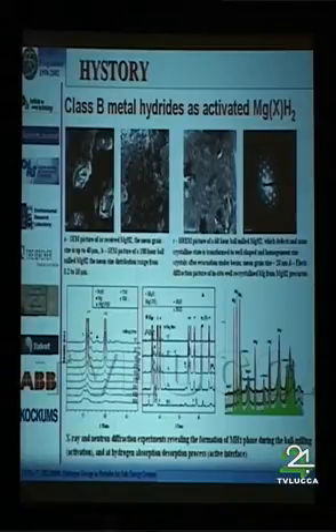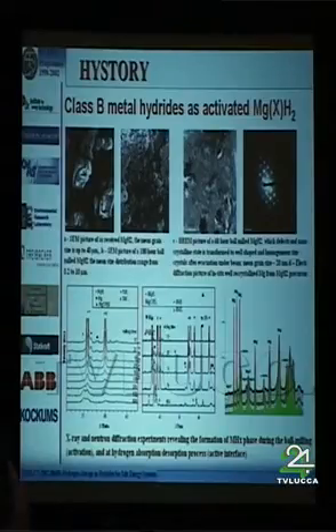So the mechanism is effectively a door mechanism, not exactly a catalyst mechanism, but hydrogen penetrates into the grain of magnesium via the so-called catalyst materials. So we have systematically analyzed the kinetics, and so we can get, for example, 80% of hydrogen uptake in the magnesium in about 2 minutes when the ball milling has been properly achieved, and using properly the good catalyst and the size of the grains of a good catalyst.